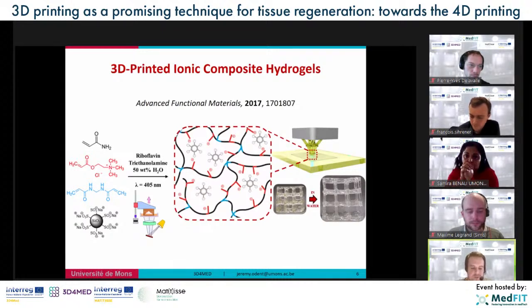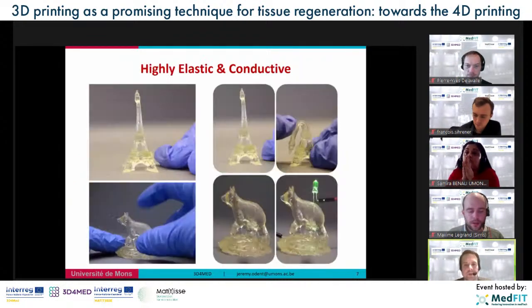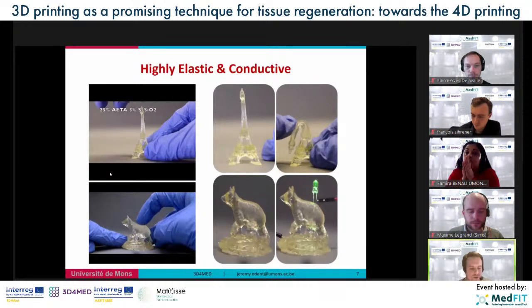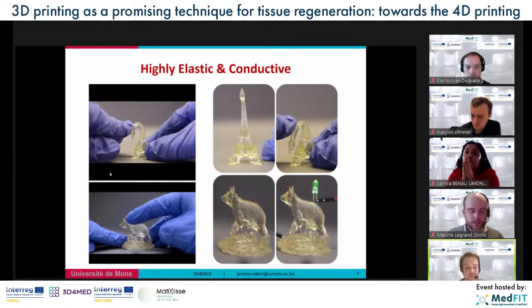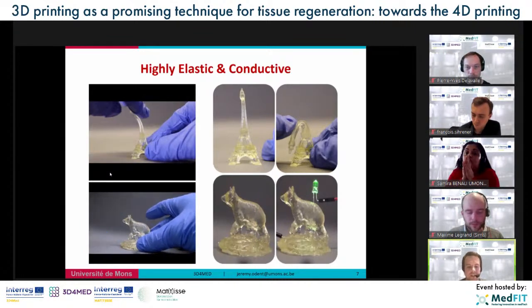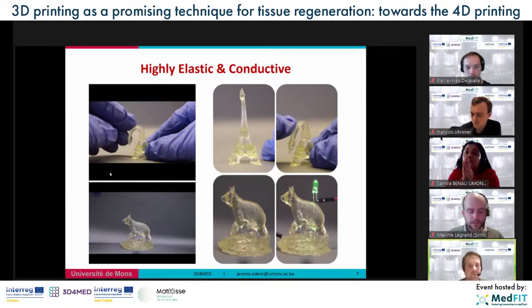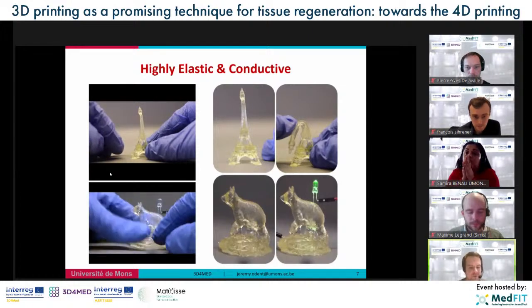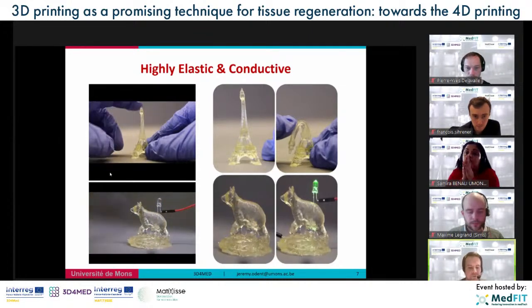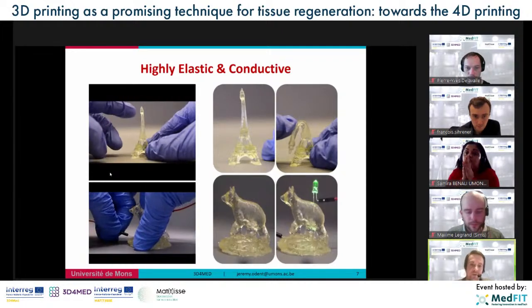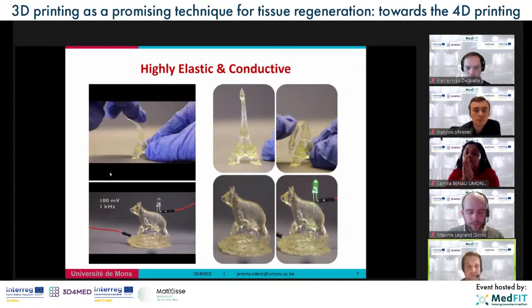The sulfonate group will interact electrostatically with the ammonium group. So we endow the system with dynamic reversible interactions, which is of great interest to promote high performance. As a result, the resulting 3D printed ionic composite hydrogel is not only highly resilient, but also ionically conductive, as you can see on the video. To demonstrate the resilience, we 3D printed an Eiffel Tower that we repeatedly stress to very large deformation.